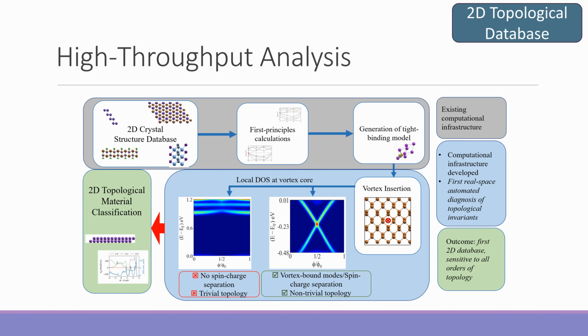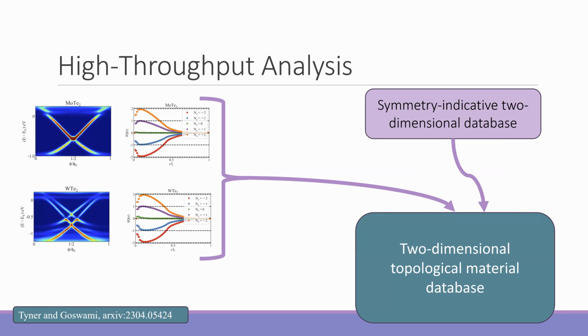And the results were pretty exciting. There were a lot of interesting materials that we found along the way here, and most of them are contained in this archive paper. Some interesting ones in particular were this 1H phase of the transition metal dichalcogenides. That was exciting because those have band gaps that we're interested in, right around 1 eV. But there are more materials, as I said, in that archive paper.